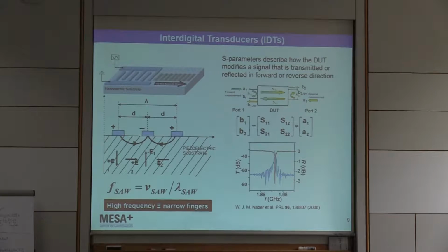But it's quite tedious. The point is that on one side you have to make very small scale features. If you go into the 100 nanometer regime wavelengths or so, the individual fingers need to be on the order of tens of nanometers. But at the same time, to get a sufficiently large quality factor, you need many of those fingers, on the order of hundreds, over typically tens to hundreds of microns distance. That's quite challenging for E-beam lithography, with things like proximity effect and drift over time. So we started thinking about an alternative method.